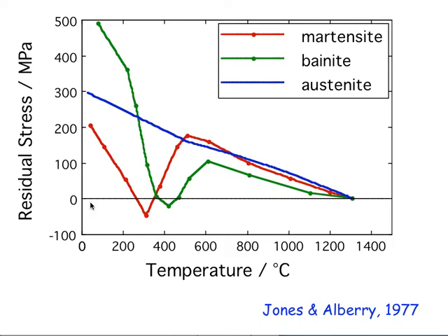So I want to make my weld martensitic, which would raise alarm bells immediately, because you're not going to be allowed to do heat treatment on an oil rig. So you want it to be martensitic, and you want it to transform at a temperature which is not too far away from room temperature. So how can I produce a nice martensite which will be nice in its untempered state? Very little carbon. So very low carbon, and therefore we are going to have to use expensive alloying elements. But the expense of alloying elements in a weld is actually quite small, because you are using small quantities of material to fill in the gaps. And if you solve the problem of residual stress and so on, then that's a huge gain.